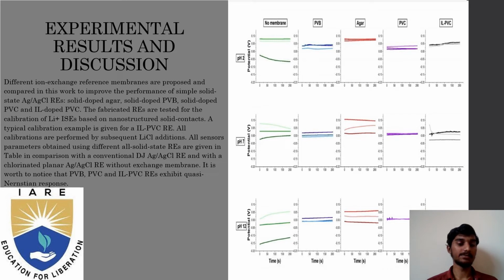Now let us go ahead with experiment results and discussion. Different ion exchange reference membranes are proposed and compared in this work to improve the performance of simple solid state electrode of Ag/AgCl: solid doped agar, solid doped PVB, solid doped PVC, and IL doped PVC. The fabricated REs are then tested for the calibration of Li+ ISEs based on nanostructured solid contacts. A typical calibration example is given for ILPVC RE. All calibrations are performed by subsequent LiCl additions. All sensor parameters obtained with different all solid state REs are given in the table below.